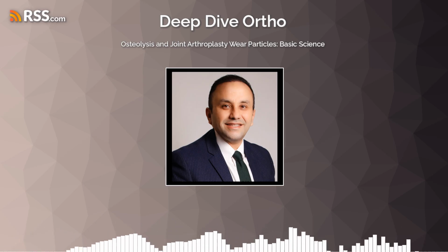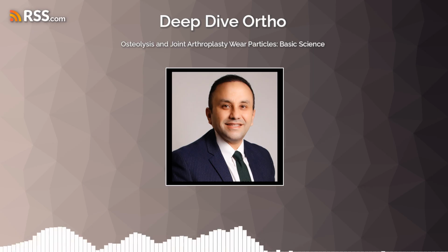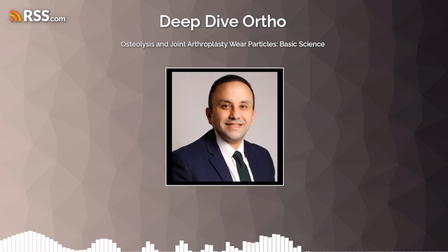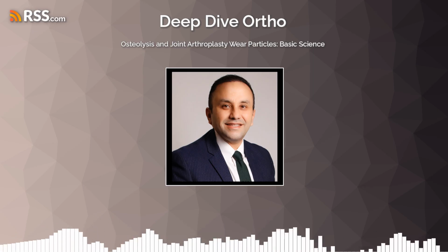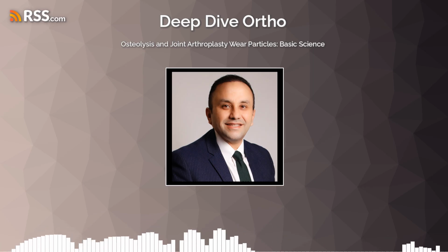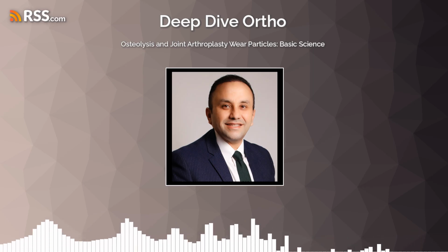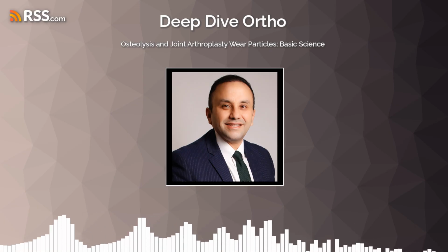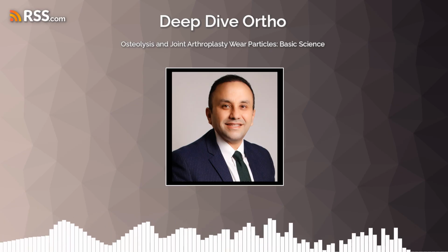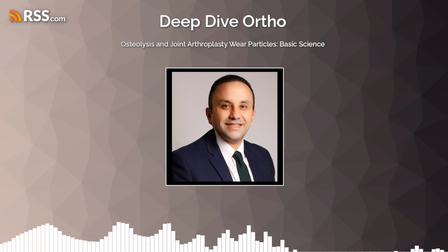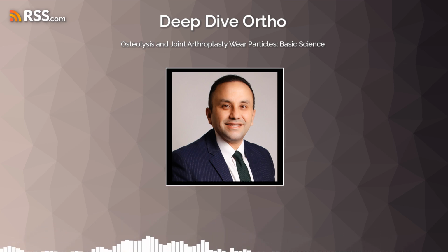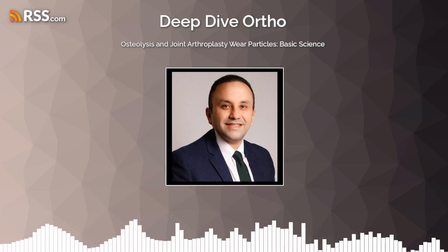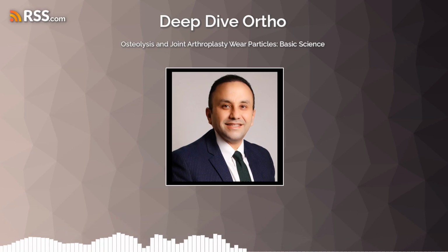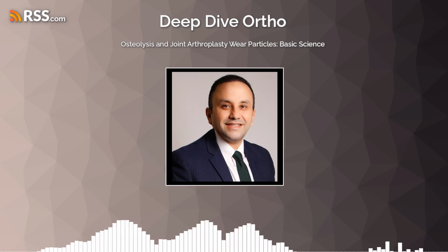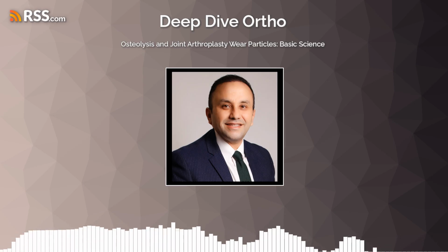Okay, that's linear osteolysis. What's the second pattern? The second pattern is expansile osteolysis. Here, the bone loss appears to actively expand into the surrounding tissue, creating larger, more irregular lytic lesions. These often look like growing bubbles or cysts or even large amorphous defects within the bone around the implant. So much more destructive looking volumetrically. Yes, quite. This expansile nature strongly implies a more aggressive, perhaps contained, inflammatory response that is actively eroding significant volumes of bone.